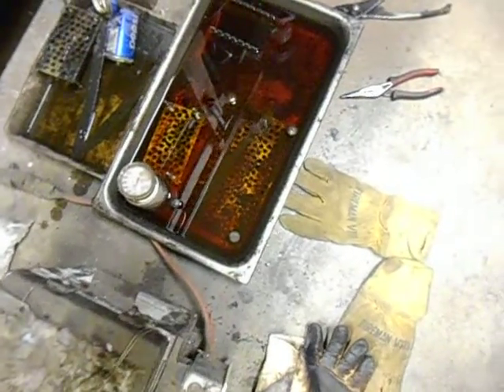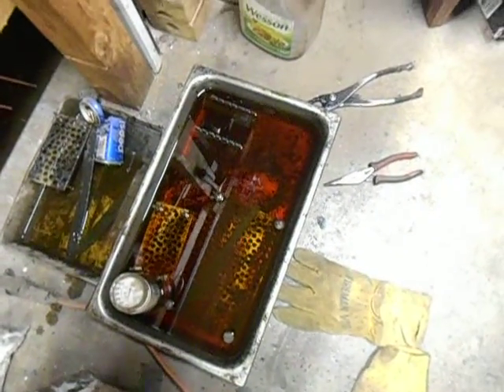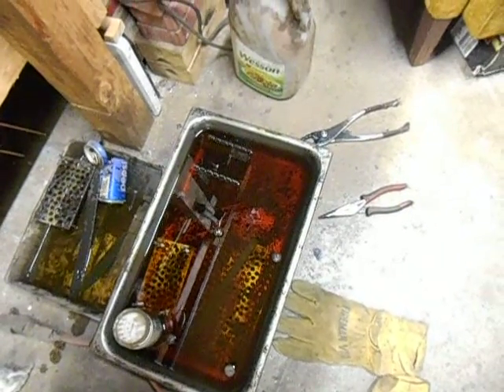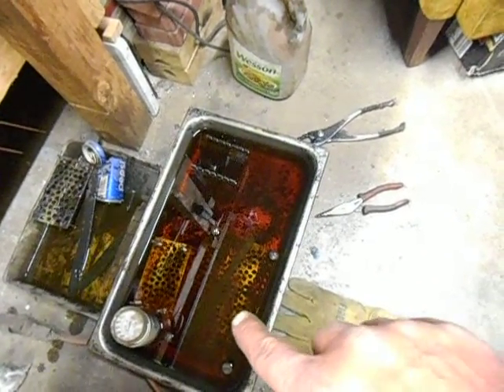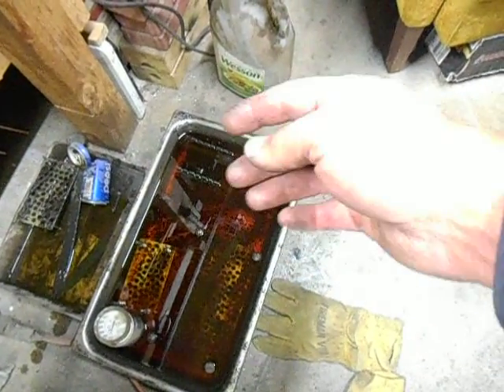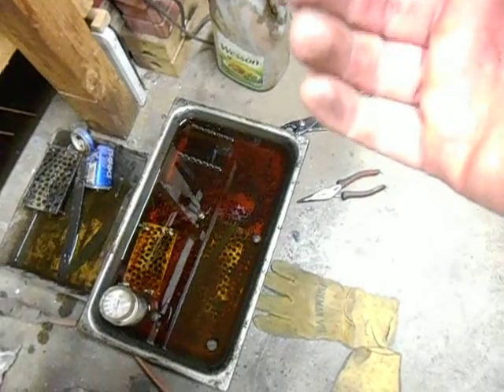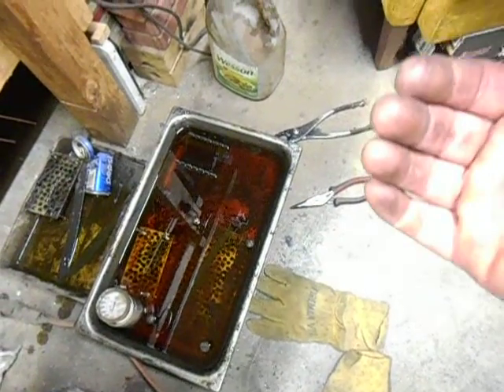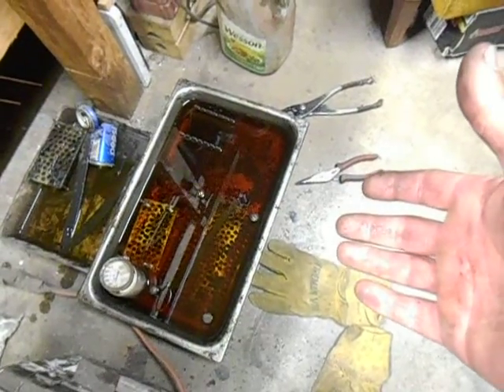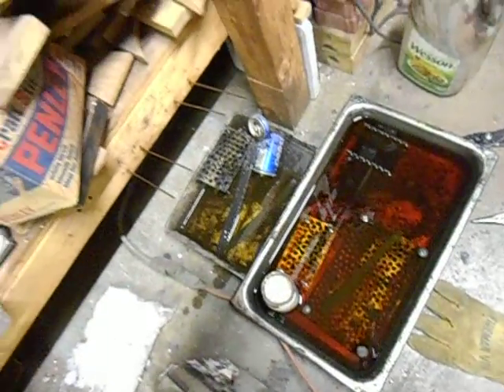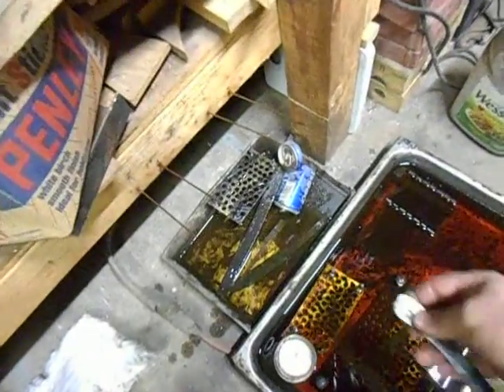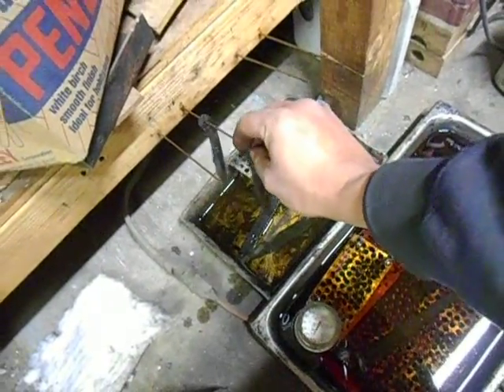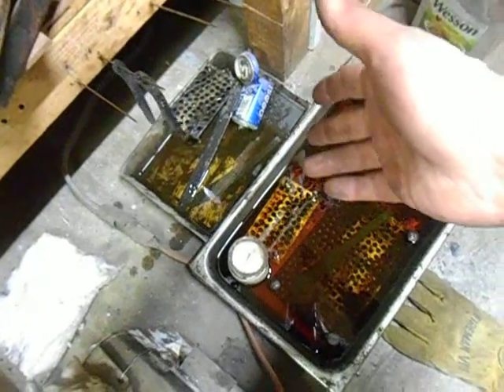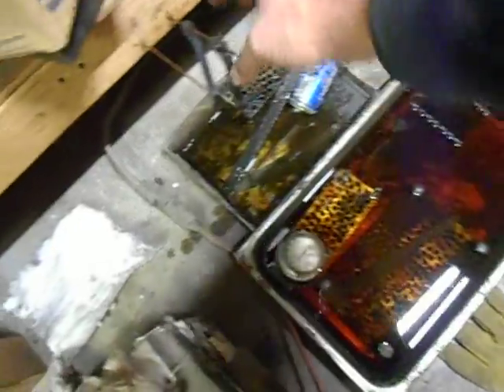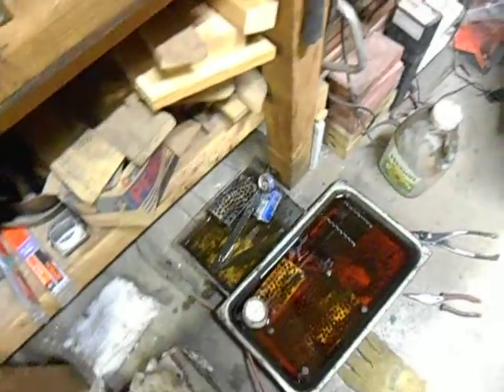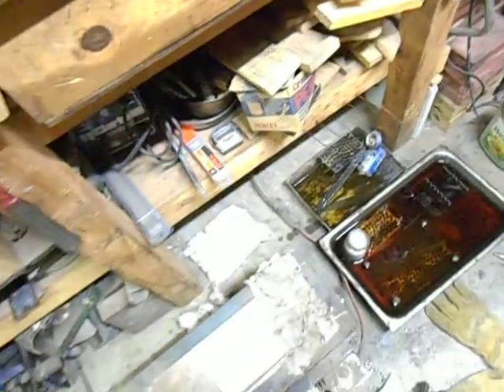There's a thermometer and a couple of regulating plates. That right there is a rack for after you quench the blade, then you move it over to where it's spine up inside the holder, and that holds the blade edge down, spine up, until it's cooled to the temperature of the oil. Then they get pulled out and hung on these little pins right here, and the oil drips off of the blade into the pan, and then once they're cool to the touch, I pull them out, wipe them off with a rag, file test them, and then they'll go into the tempering oven.